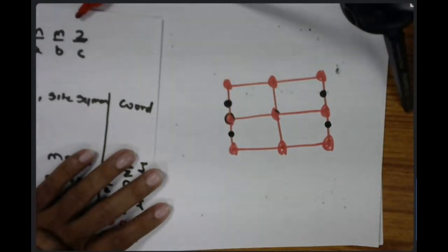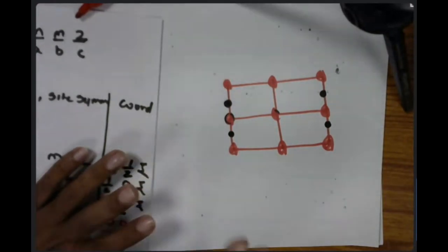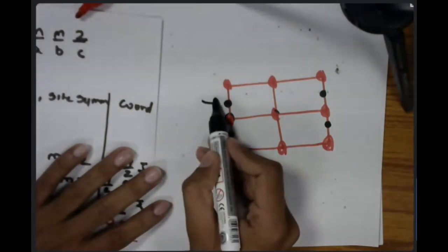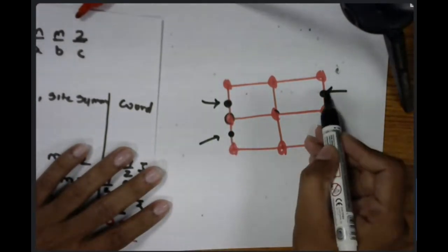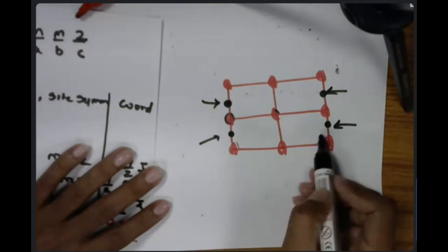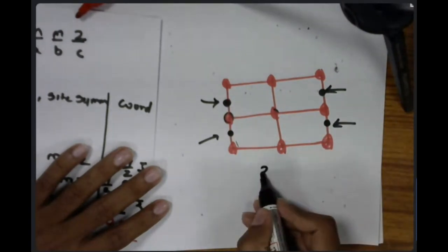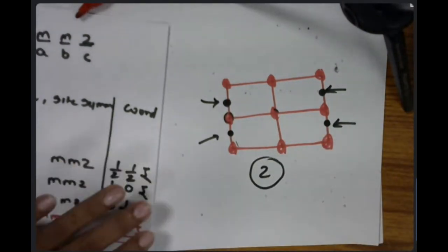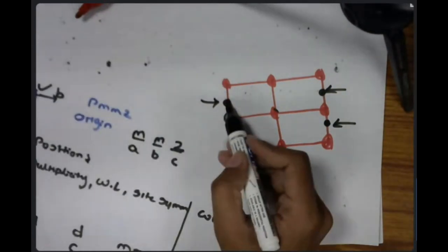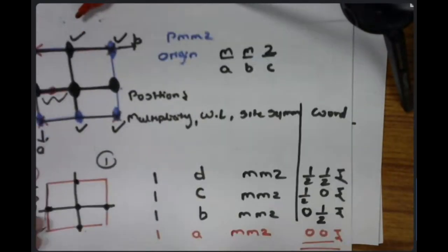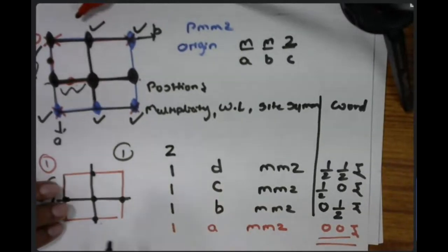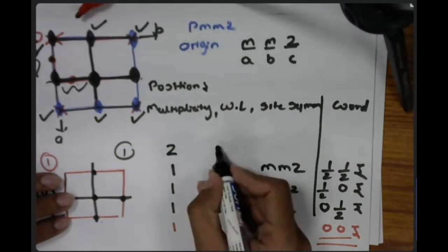Alright. We can see that this is going to contribute 1 by 2, 1 by 2, 1 by 2, and 1 by 2 to our unit cell. So effectively, there are the two. Effective contribution is 2. So the multiplicity of this particular site, if I place a point on this site, is 2. Let's move ahead in the Wyckoff operator, and we can write from D,